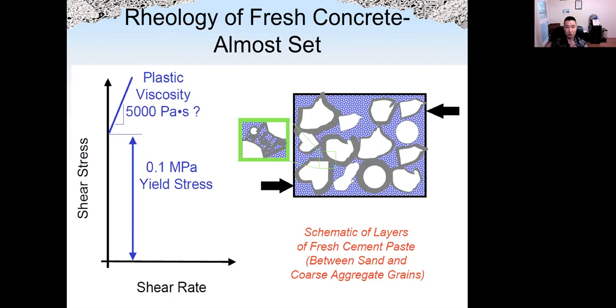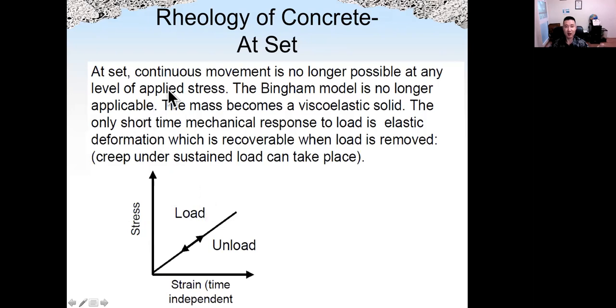So when the concrete almost sets, the particles will connect to each other. We have a transition from fluid to semi-solid. So we can see the yield stress further increases, and so does the plastic viscosity. At the set time, continuous movement is no longer possible, so the Bingham model is no longer applicable, and the total mass will change from a liquid to a viscoelastic solid. We could have an elastic response, but this is due to elastic strain and also creep, but there's no shear rate and shear stress.